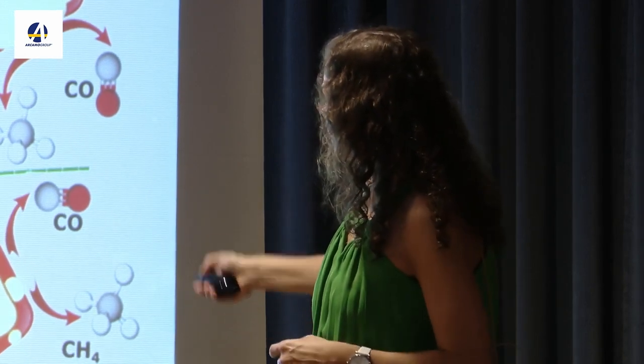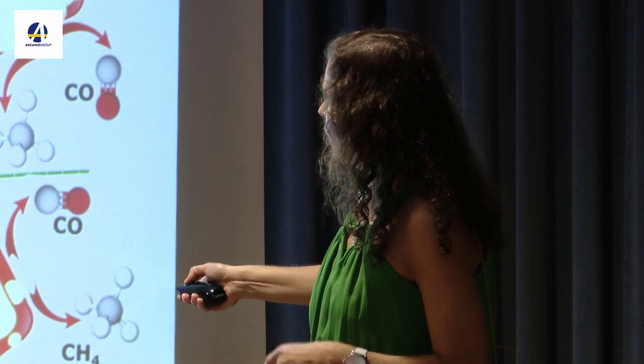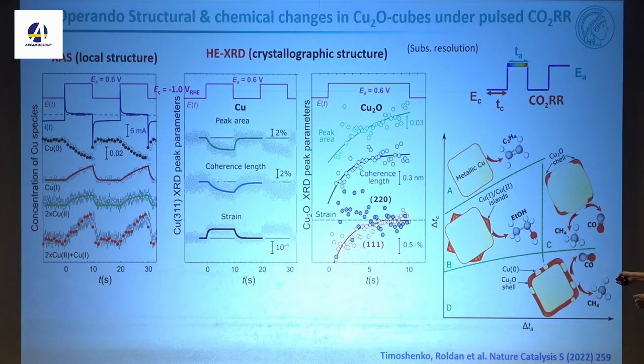If in the region where I'm making ethanol, I don't have metallic copper, I have metallic copper in close contact with copper 1 and copper 2 islands, highly disordered, XRD invisible, only XAS visible. And if you start growing a very thick oxide layer, this is here the length of the cathodic pulse. This is here the length of the anodic pulse, the different regimes I showed you before.